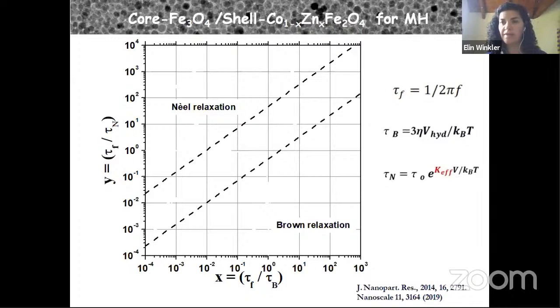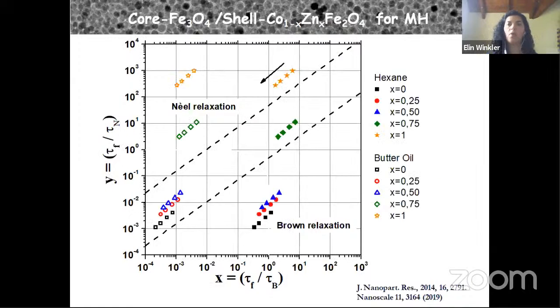So we calculated that for our samples and put them in this graph. We have these two sets of points. The solid points correspond to the nanoparticles dispersed in hexane. As we observe, these three samples, the samples rich in cobalt, present relaxation by Brown. On the contrary, when we disperse the samples in butter oil, we shift toward the left of the graph, because we increase the viscosity, so we increase this time and we move in this way. So in this case, the mechanism is mainly Neel relaxation.